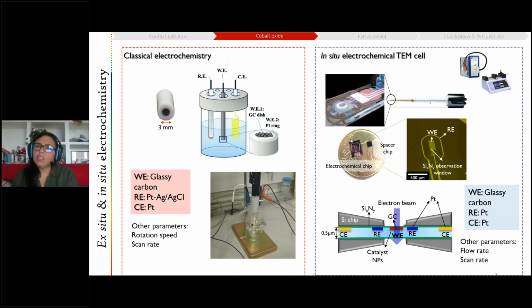So as I was mentioning before, thanks to the holder of prototypes, we have a miniaturized electrochemical cell where we can have a working electrode of glassy carbon, a reference electrode around, out of the observation window, made of platinum, and that's why we try to do our experiments ex situ as well with a platinum reference and a counter electrode of platinum as well. And we are able to pass the electrolyte through the two windows and connect everything to a potentiostat and do the electrochemical measurements while we observe our material.